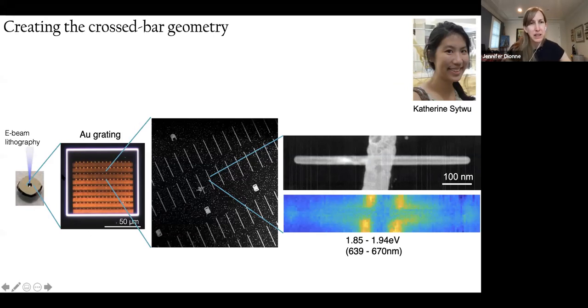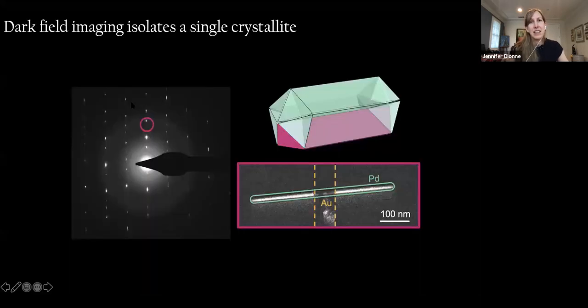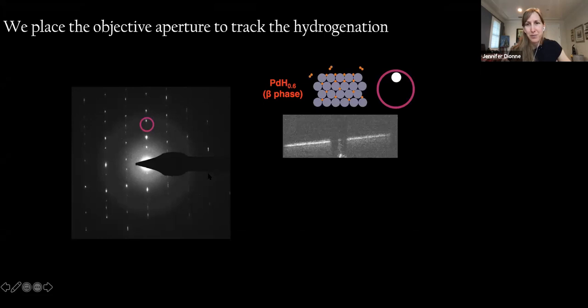You can also see here when we fabricate that gold grating that the resonance is mostly in the red. And then what we do is use dark field imaging and electron microscopy to isolate individual crystallites within these nanobars, so that way we can follow the hydrogenation and dehydrogenation of single crystallites.